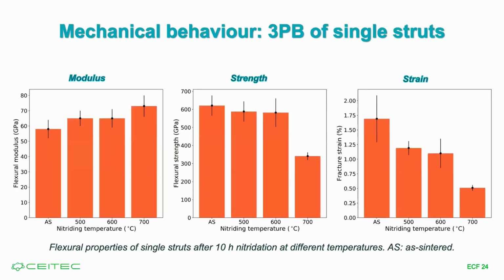And here are the results from 3-point bending of single filaments. And this is kind of expected. You nitride them and the stiffness increases with increasing thickness of nitriding layer. But this is quite surprising because the strength is decreased. But this is maybe because it's open porosity, so we have really volumetric nitridation. And here when it goes to fracture strain, we see decrease compared to as sintered state, and abrupt decrease for 700 degrees Celsius.